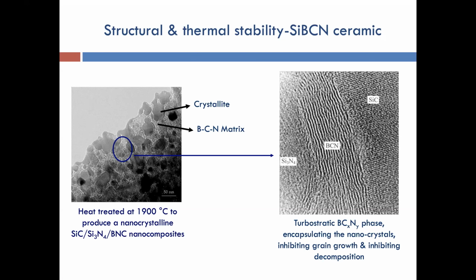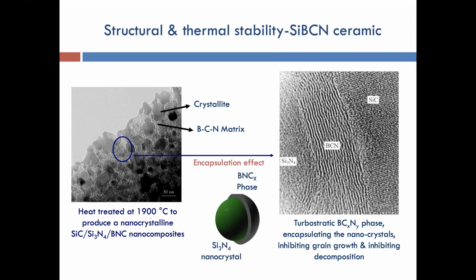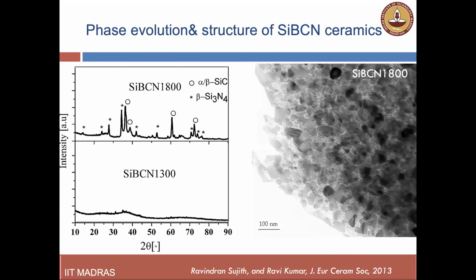In fact, thermodynamic calculations predict decomposition of silicon nitride at temperatures around 1800 and so on, but you will see that even at 2000 degrees Celsius, silicon nitride does exist, and that's what I showed you in the X-ray diffractograms. And what we believe is that this BNC phase, or the boron, carbon, nitrogen turbostratic layers, simply encapsulate the silicon nitride crystals, completely protecting them from any decomposition reactions. And therefore, the material in its entirety is quite stable till 2000 degrees Celsius. And there, you have the material easy to be used for such extremely harsh temperature applications.